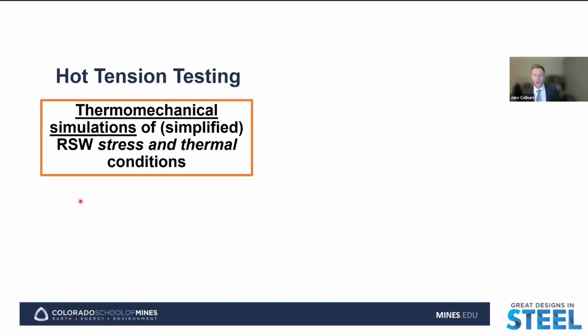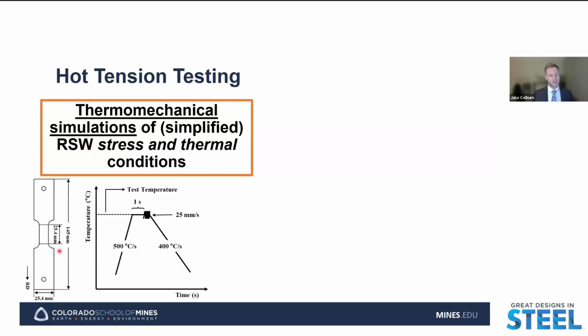As we begin looking at the LME testing, one of the first tests that we can do is hot tension testing, which is essentially a thermomechanical simulation of the resistance spot weld stress and thermal conditions. Of course, this is a simplified condition of our stress and thermal states, because many of the stress and thermal states that we have during resistance spot welding can be much more complicated than just the uniaxial tension that we're going to be applying during this test.